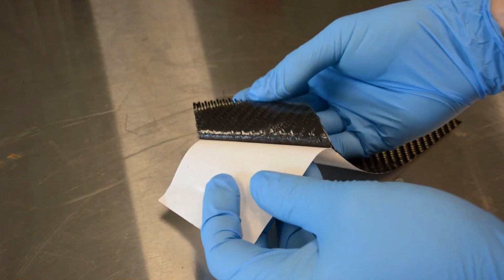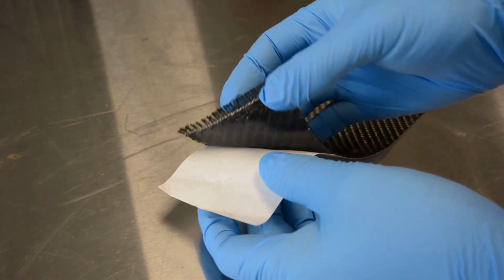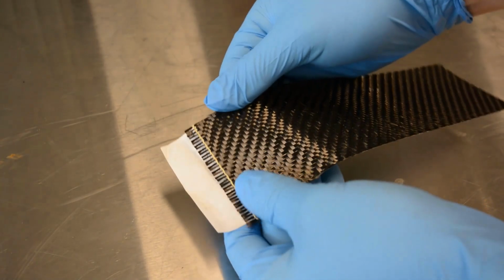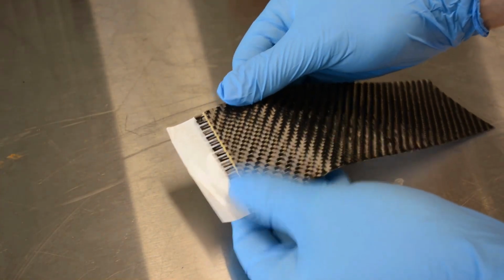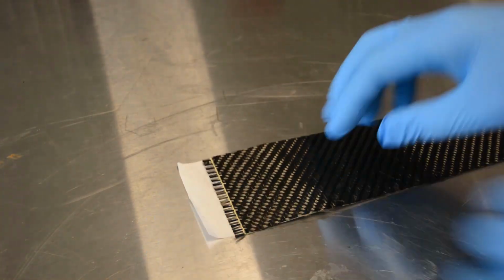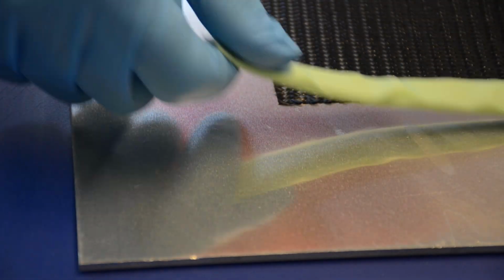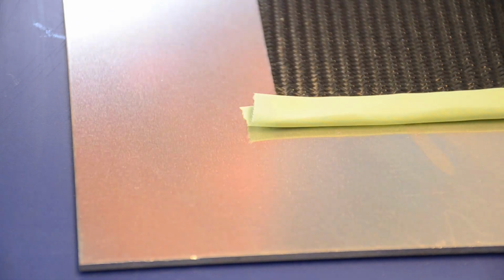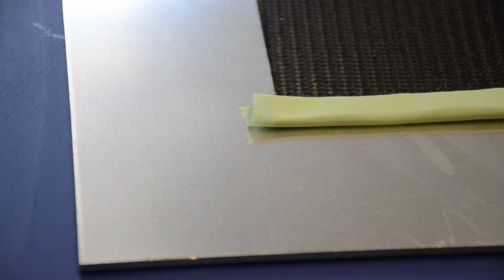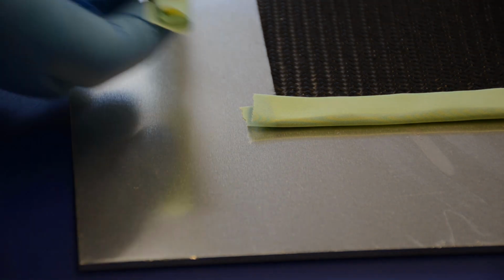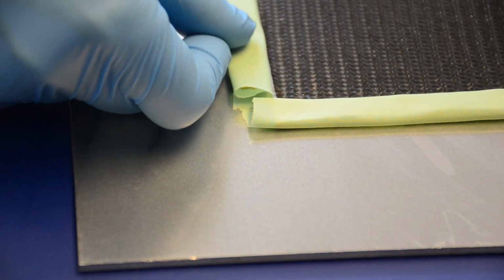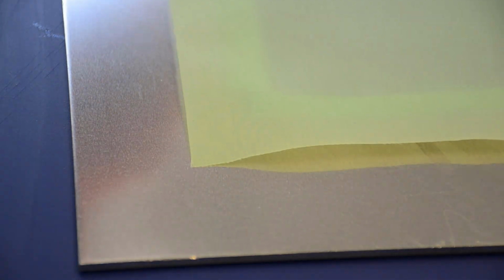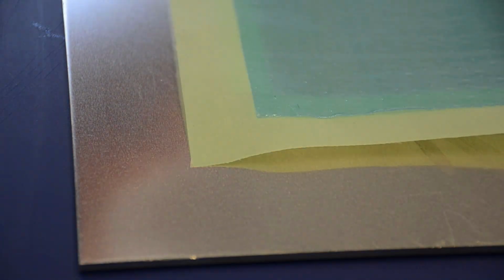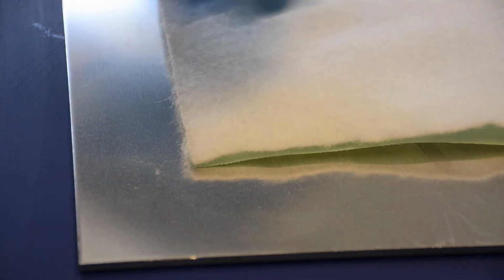Prepregs designed for vacuum-only processing, also known as out-of-autoclave processing, typically have regions of dry fiber to aid in air evacuation. Prepreg is more permeable to air in the direction of the fibers rather than through the thickness of the plies, which comes into play when placing the consumables for maximum air evacuation. For some applications, a permeable material is placed adjacent to the part under the release film to allow air to more easily flow out of the part, therefore reducing defects.